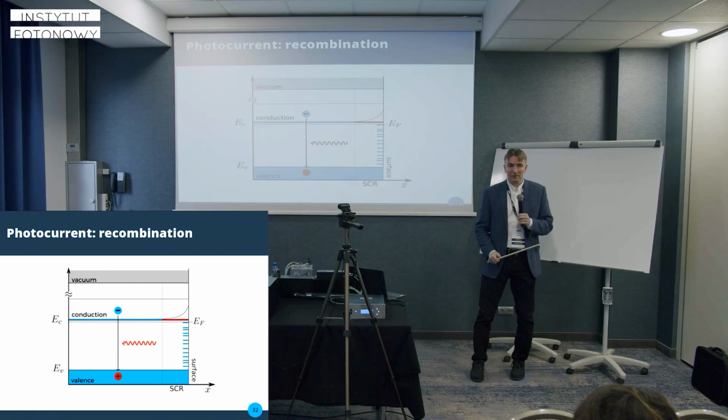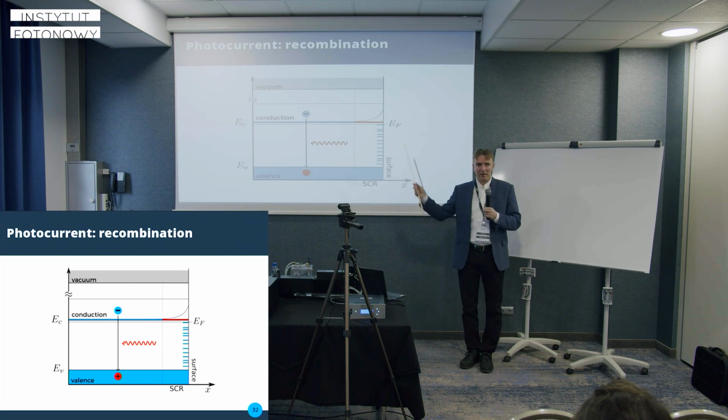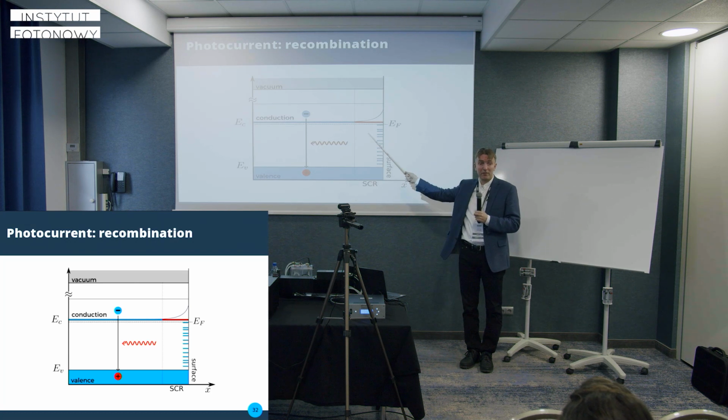This electric field can intervene when we excite this electron, before it has a chance to go back to its initial state. Those two wave functions, the blue one and the red one, will be shifted apart so they no longer overlap. And there is little chance for the recombination.